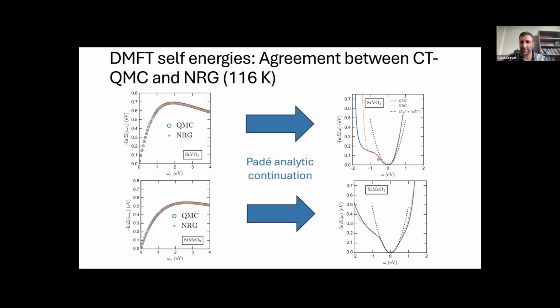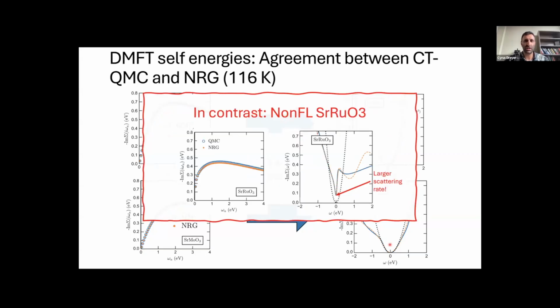So we also see this Fermi-Liquid-like omega squared dependence of the real frequency self-energy. And so at the temperature of this calculation, which is 116 degrees Kelvin, we could say that these materials are in the Fermi-Liquid regime. Of course, we can do better than just fitting a parabola to the low frequency behavior. Just to contrast a material that I'll show a little bit later, the non-Fermi-Liquid strontium ruthenate has quite a different behavior and notably a much larger scattering rate at zero frequency. So I'll come back to that in a second.